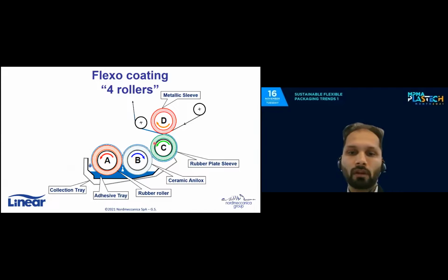Here we have a rubber roller, a ceramic anilox, a rubber plate sleeve, and a metallic sleeve. Both the rubber roller and the ceramic anilox are dipped inside the adhesive. Both rollers collect the adhesive, and here there is the first gap, the first calibration of the adhesive thickness. Then there is a second calibration between the ceramic anilox and the plate cylinder, and then the adhesive is transferred directly to the web. Again, even this roller is intended for high solid adhesives.